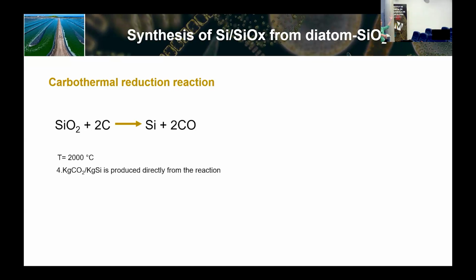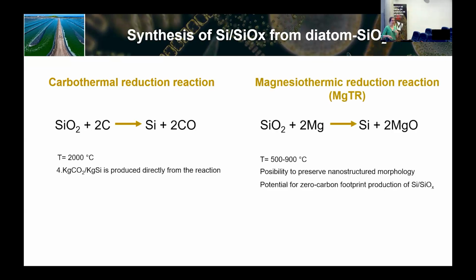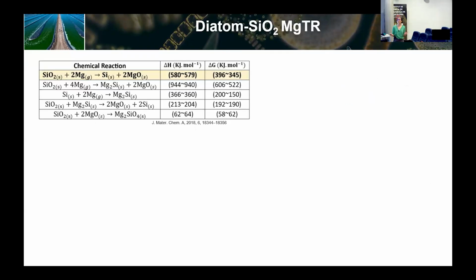And then you have the other carbon footprint that comes from the electricity we used, and we made use of carbon for that. So we're trying to go to another reduction, a magnesiothermic reduction reaction. In this route, we use magnesium as a precursor, and we can reduce the silica to silicon or SiOx at temperatures that are much lower than these 2000 degrees. This is super important because we want to preserve the morphology of the diatoms. That's why we use the nanostructured material as a feedstock. If we cannot keep the morphology, then it won't make any sense. So the idea is to play with this reaction to preserve the morphology, and also to go for a zero carbon footprint synthesis of the material.